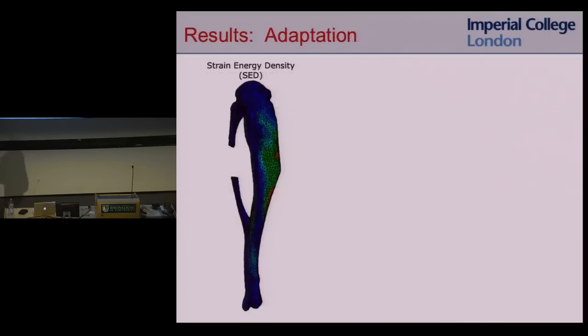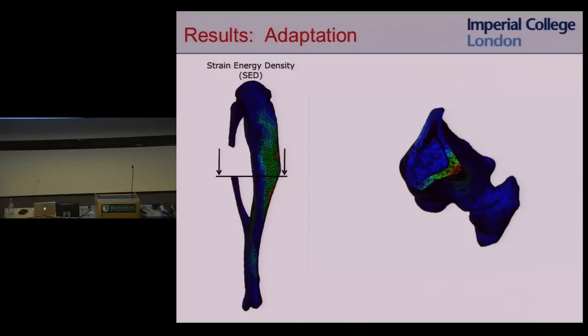So how do we do on the adaptation? So here, again, I'm using strain energy density as a stimulus. So if we look, most of the interesting stuff is going to happen around here, where there's high stimulus. You would expect where there's high stimulus, that's going to promote growth. So what I'm going to show is in cross-section. This is a cross-section looking down on those arrows. Here's the cross-section of the bone. It's hollow in the middle. This region right here is high stimulus, so that's where you're going to expect the bone to grow.